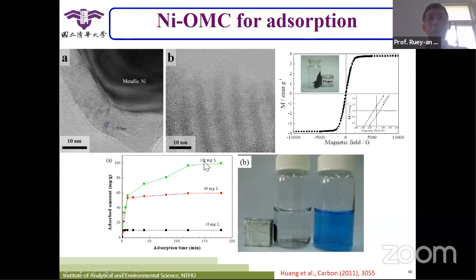So here we put just 100 milligrams of methylene blue, and they can remove it in 2 hours. So the efficiency is quite good. You can see that the absorbed amount is almost 100 milligram per liter, meaning that all of it can be removed.